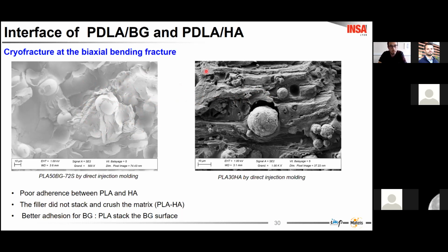Just for information, to obtain these images, I did a cryofracture at the biaxial bending fracture. So I fractured the biaxial bending sample in nitrogen, and here we can observe what happened at the fracture of the biaxial bending test.